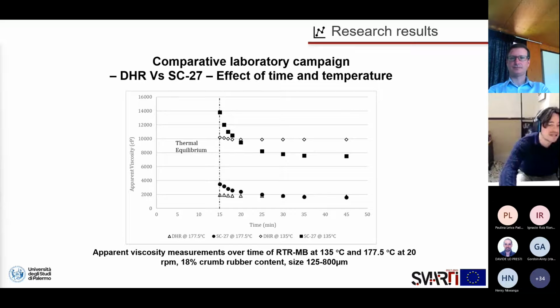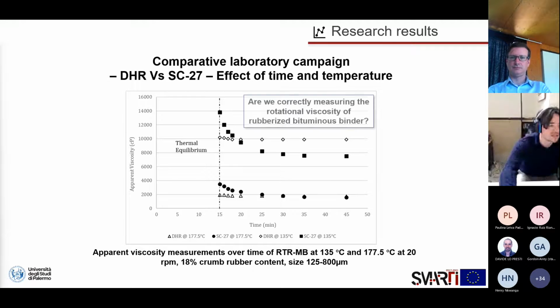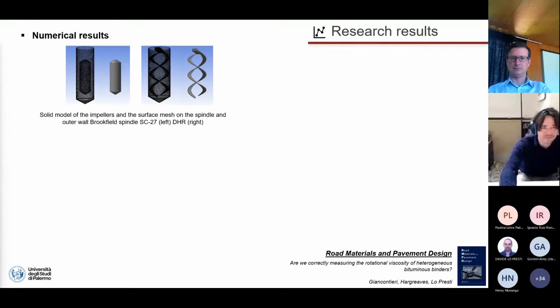This means that the sample might be suffering sample instability phenomena. From these results, the question arises if we are correctly measuring the rotational viscosity, for example, of rubberized bituminous binder. To provide further insight, parallel to the experimental campaign, a numerical model reproducing the laboratory test was developed.